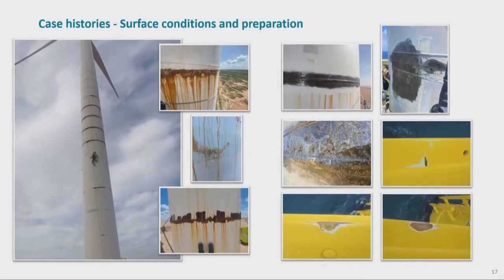So we have coatings that have passed the test and so on, and then we get this, and then we get the reverse. We fail the test, but in reality, we go back and repair all these with good results. 5 years doesn't seem like much, but we know that the technology has been around for about 25 years, so we know it has worked in other areas. We just redesigned it for this environment. So this shows you roughly what we do. We go back here, and we look for these scribes, and then we repair them.